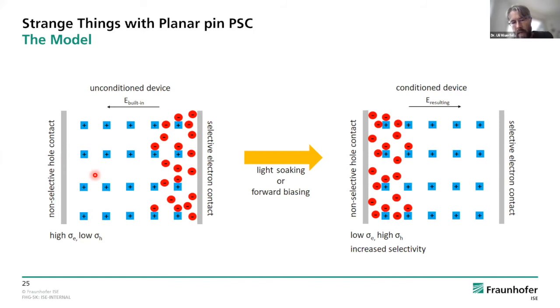Now, if we light soak, or which I didn't mention, forward bias our device, we switch on the light, we keep the solar cell under open circuit condition, like in the experiment I showed you, where you saw the transient rise of the open circuit voltage, then due to the build-up of electrons and holes, the built-in voltage is weakened. It's reduced. It can even flip to the other side. That depends, of course, on the exact parameters. But for sure, the built-in voltage which you have in the beginning is somehow getting smaller. Now, this then leads to the situation that these negative ionic species would rather go back to this side.